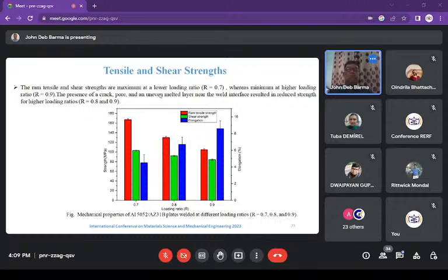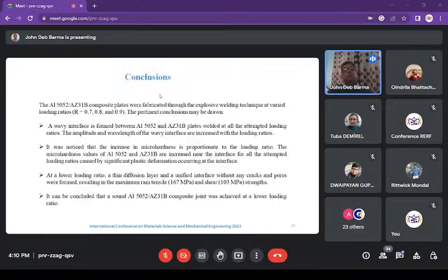But in contrast, at higher loading ratios, we have seen apparent ductile rupture characteristics with a massive number of dimples, or you can say grooves or cracks, on the interface. The appearance of these grooves and the solidified melts of the welded sample also agree with the reports of earlier research. In addition, the elongation to fracture of these AZ31B and Al5052 composite plates increased significantly as the loading ratio increased. So these are the points that you can draw as conclusions.